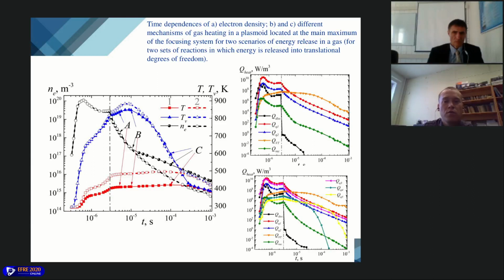The dynamics of the gas translational temperature in the active phase has a stepwise form. A sharp increase is observed in the time interval of the formation of the first plasmoids, to 358 kelvins and 396 kelvins respectively for the 2 sets of gas heating mechanisms. Then by the end of the microwave pulse, the temperature increased to 390 kelvins and 460 kelvins respectively for the first and second sets of gas heating mechanisms.